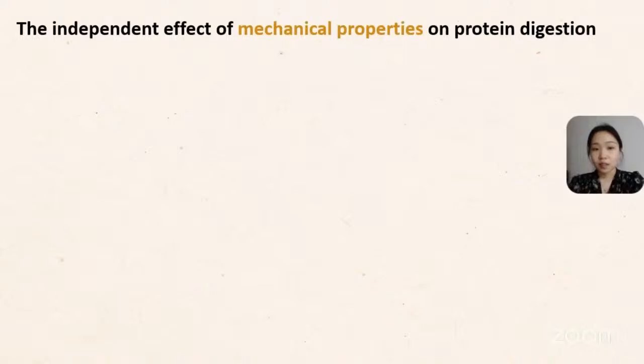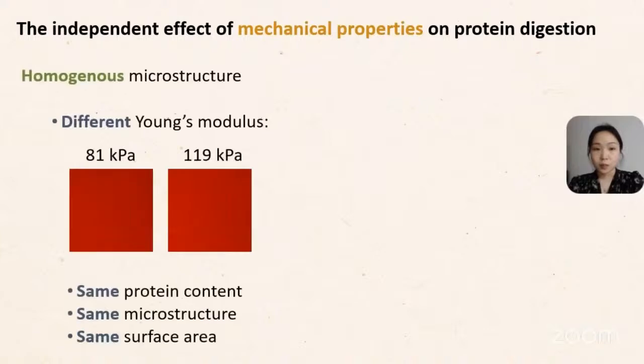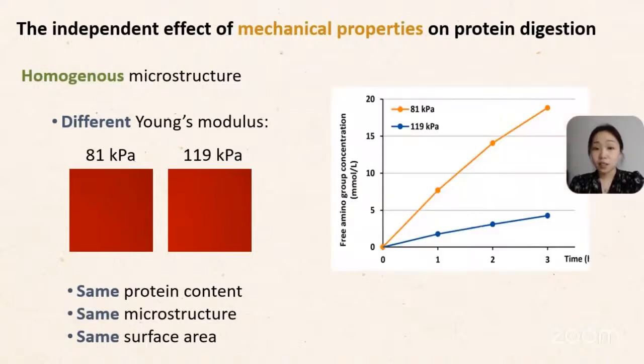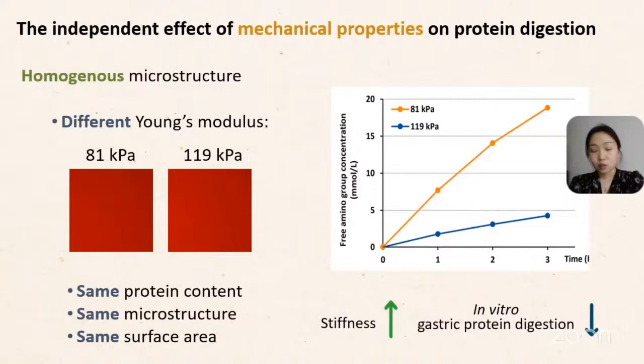Then we studied the independent effect of mechanical properties. We started with homogeneous gels. So we had these two gels with the same homogeneous microstructure, but different Young's modulus. One gel is harder and the other one is softer. As expected, the softer gel was more digested than the hard gel. This means for the homogeneous gels, increasing the Young's modulus or the stiffness could hinder the in vitro gastric protein digestion.